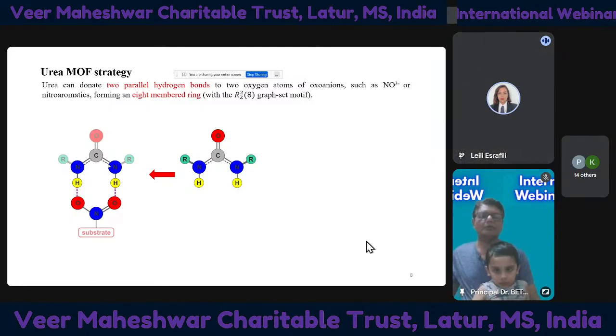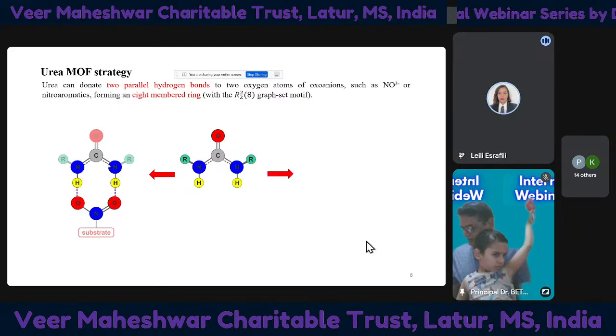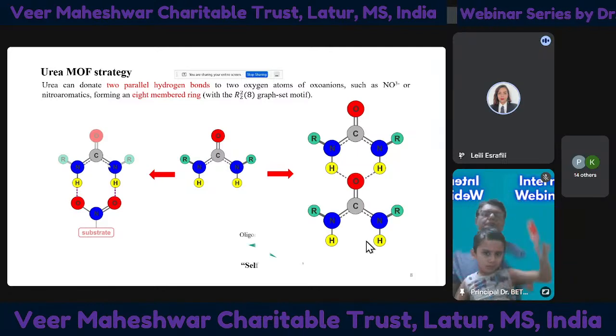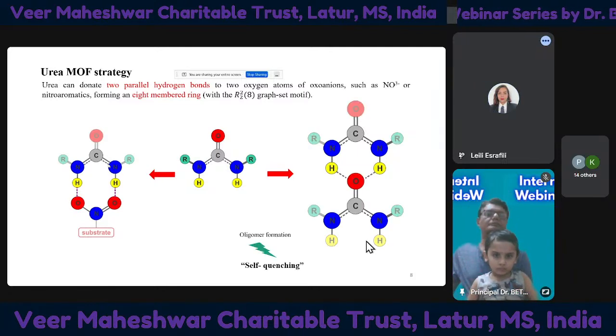In organocatalysis, this interaction activates the substrate by increasing electrophilicity, essentially making a reaction occur faster by lowering the energy barrier. However, sometimes there is a major problem too. Urea molecules tend to hydrogen bond with each other, as you can see here, and this leads to aggregation and self-quenching, which reduces catalytic activity and efficiency.